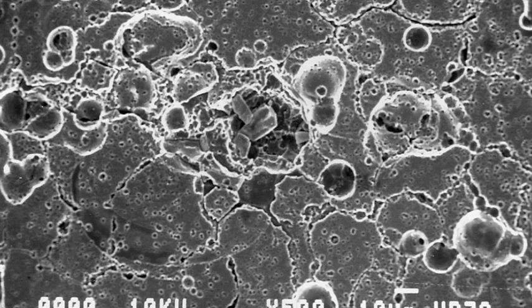Now if we clean the sample with nitric acid, we can remove this white corrosion product. And there we see the pits beneath each of the chimneys. And inside the pits, we can actually see the second phase particles which are lit up here in this image.